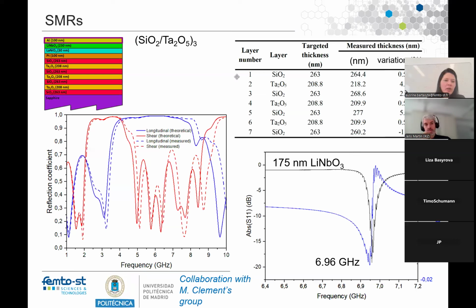We targeted a 230 nanometer thick lithium niobate film. I did not have so many mirrors, and I missed some steps for bottom electrode preparation and so on. Then I did my lithium niobate growth, the clean room cooling water stopped during the night, and my machine stopped at 175 nanometers. So we missed the targeted thickness. The mirror was also annealed, because the mirror was done at room temperature. The thickness should be moved away from the absolute values we expected, so probably the mirror was not perfectly reflecting the wave.